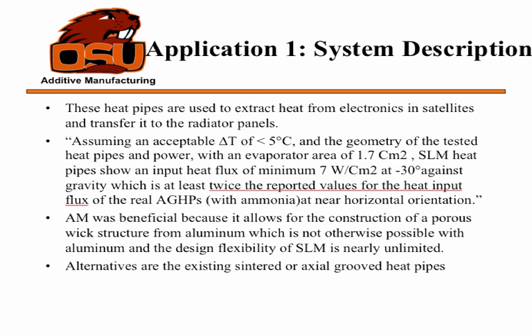It says, assuming an acceptable delta T, which you need to drive the thermal gradient, the geometry of the tested heat pipe and power with an evaporator of 1.7 square centimeters, SLM heat pipes show an input flux of 7 watts per square centimeter at negative 30 degrees against gravity, which is at least twice the reported value for the heat pipe flux of a real axial grooved heat pipe with ammonia at near horizontal orientation. So you get really good heat transport with these selective laser melted parts.